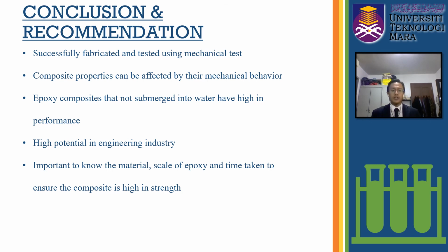In this project, we can conclude that this project was successfully achieved. It is because we have successfully fabricated and tested using mechanical tests, which are the ILSS and flexural tests. Second, the composite properties can be affected by the mechanical behavior, which means we can know that the composite material will be affected by the water submerged. The third is that the epoxy composite that is not submerged in water has high performance. In this project, of all the days submerged, the 0 days of submerge has higher performance than the others. It has high potential in the engineering industry when using this experiment.